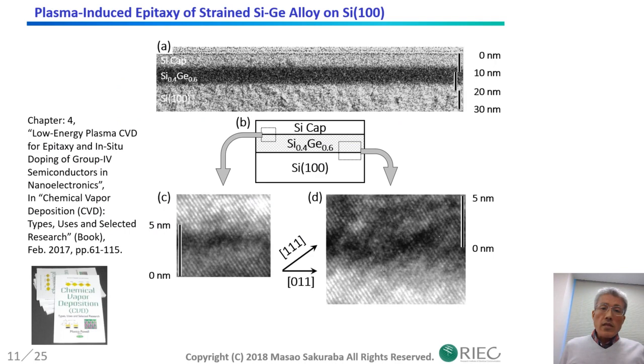This is a typical TEM picture of silicon and silicon germanium alloy heterostructure. Germanium fraction is about 60%. From the arrangement of bright dots, epitaxial growth is realized even without substrate heating.